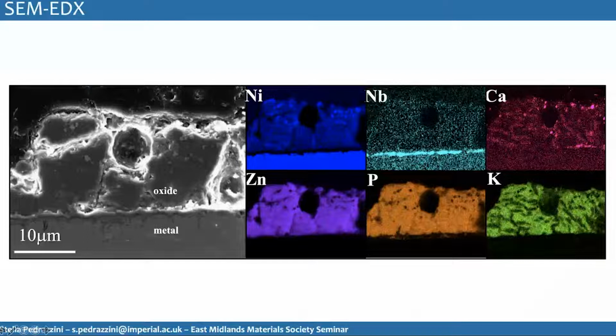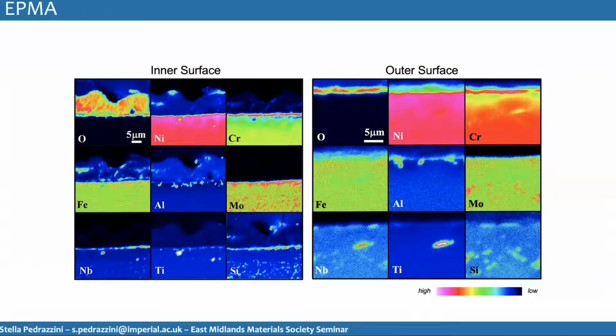To characterize something like this, I need a lot of different techniques as well, because like I mentioned before, some of them are better for light elements and some of them are better for heavy elements. So this is the surface scale, and there's the nickel is the bulk alloy. At the boundary, there's some niobium, some calcium, some zinc, phosphorus, potassium, and it's quite interesting. The surface deposit doesn't look like it's broken through. So we kind of got this sample thinking that it was going to be a corrosion failure, but we can see a deposit on the surface, but it doesn't look like the deposit has broken through.